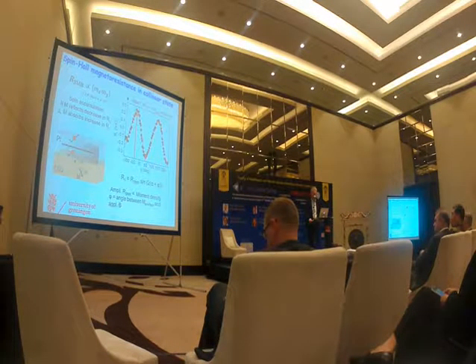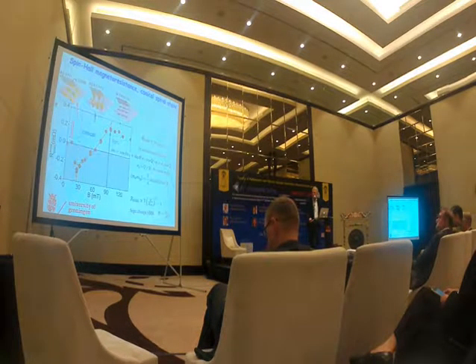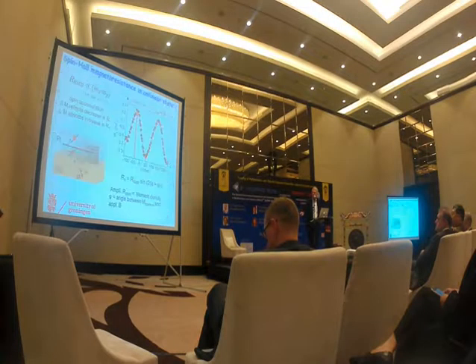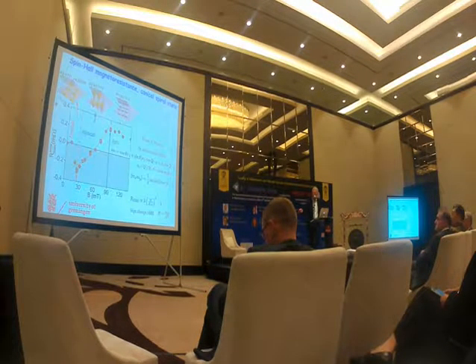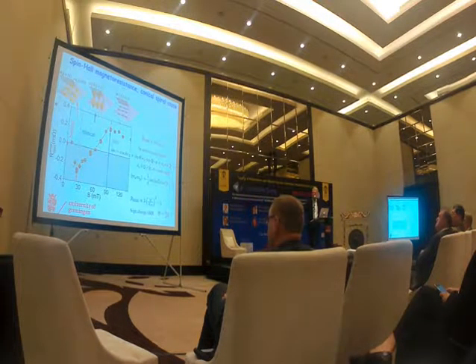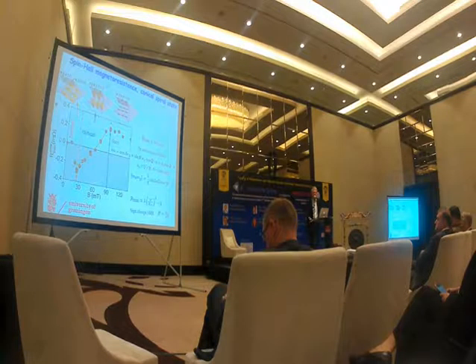We have covered the entire phase diagram of this material. We see inside the helical, conical, and ferromagnetic states, you have a dependence of your spin Hall magnetoresistance that can be modeled by modeling the magnetism of this state. So this is one example to use spin currents, pure spin currents without charge currents in part of information technology.